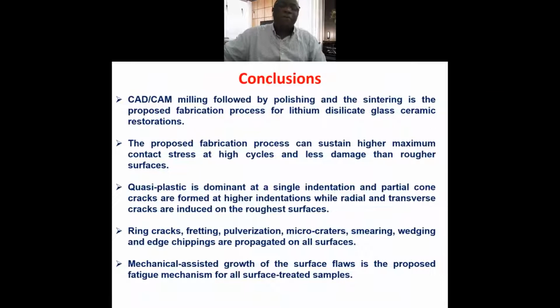So in conclusion, CAD-CAM milling followed by polishing and sintering is the proposed fabrication process for lithium disilicate glass ceramic restoration. The proposed fabrication process can sustain higher maximum contact stress at high cycles and less damage than rougher surfaces. Quasi-plastic is dominant at a single load, and partial cone cracks are formed at higher indentation, while radial and transverse cracks are induced on the roughest surfaces. So ring cracks, fretting, pulverization, micro craters, smearing, wedging, and edge chippings are propagated on all surfaces. So mechanical assisted growth of the surface flaw is the proposed fatigue mechanism for all surfaces treated.